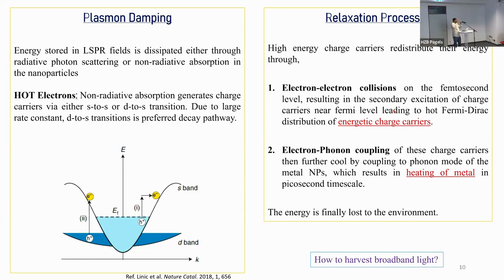And that entire energy is then converted into thermal energy, which is localized onto the surface of the nanoparticle. So again, you can carry out thermal catalysis using light by using this photothermal behavior. So either you use the hot electron to carry out the electron mediated reaction, or you can use this localized heating, which also allows you to do the catalysis.